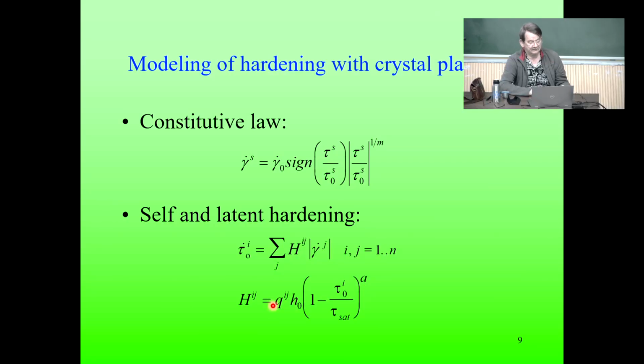And further, there are these self and latent hardening parameters, which are put into 4 categories. So basically, there are 4 parameters here. This is very sophisticated, as we showed, with very good agreement. If somebody is using this in polycrystal plasticity, surprisingly good agreements can be obtained with the macroscopic curves.